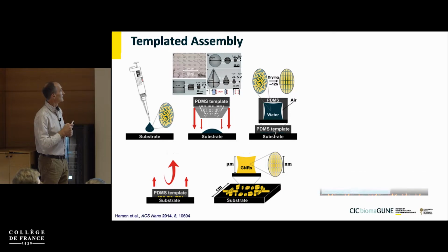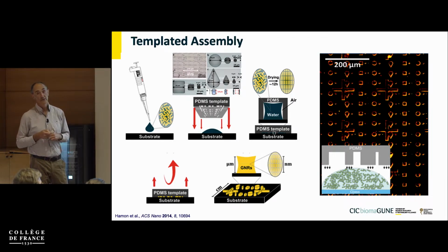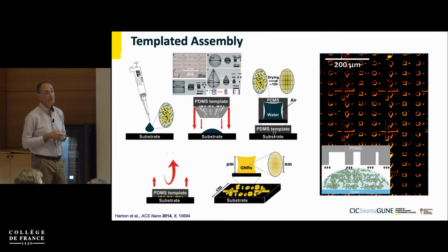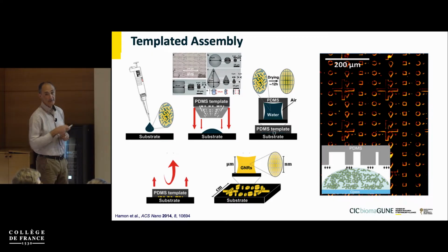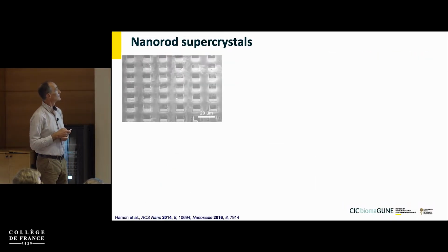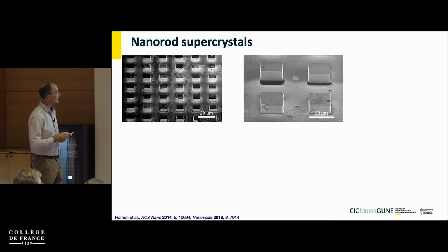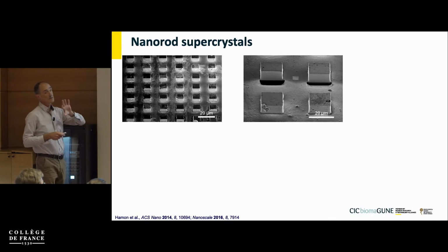And then after doing that, you obtain a dark field optical microscopy image like this, which at least shows you that the organization of the nanoparticles has somehow followed the morphology of the holes that we had in the PDMS stamp. And now you come with these samples into the scanning electron microscope, and then you find pictures like this, where actually, so this is already with a very well-defined substrate template, where all the holes were the same size and very well organized in the space.